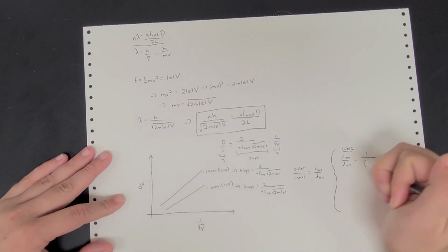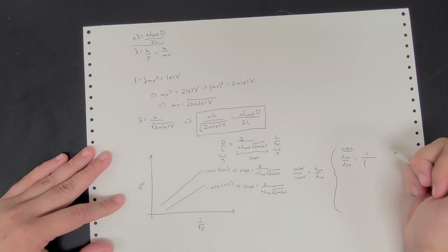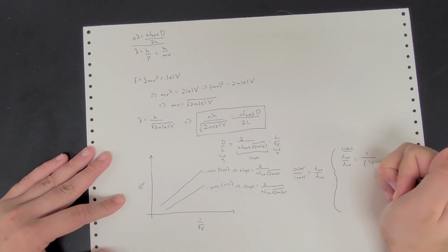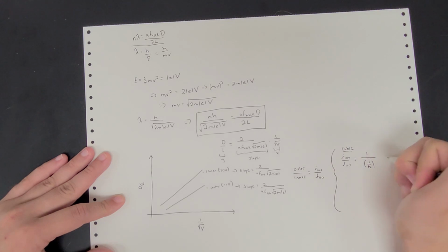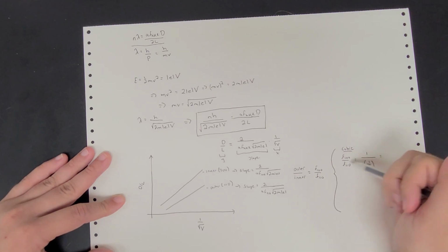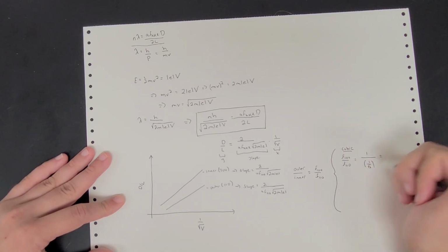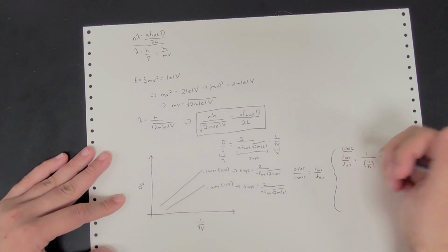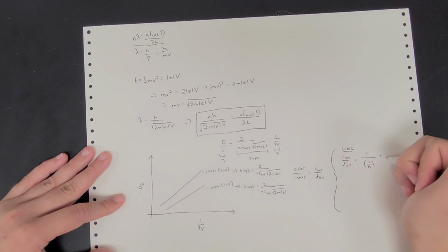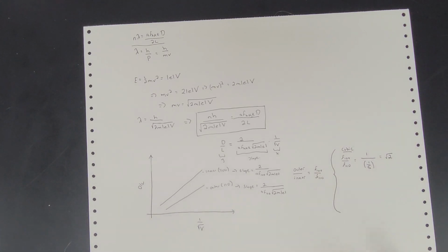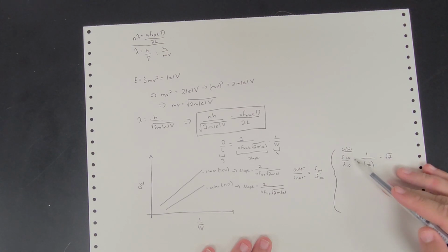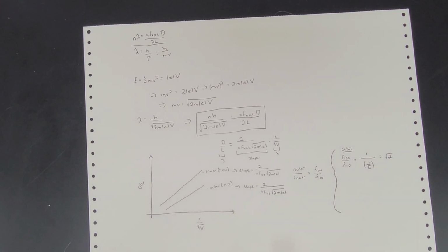And then we divide that by the F110 for that cubic one, and that's going to be 1 over the square root of 2. So if our lattice is cubic, we'll get a ratio of these two values to be the square root of 2. So if the ratio of our two slopes is equal to the square root of 2, we will then have a cubic lattice, and that'll tell us then which values to use for these two FHKL values.